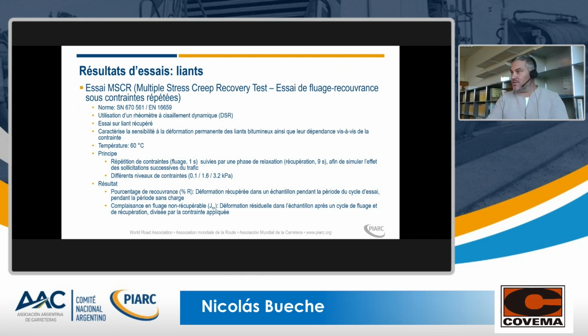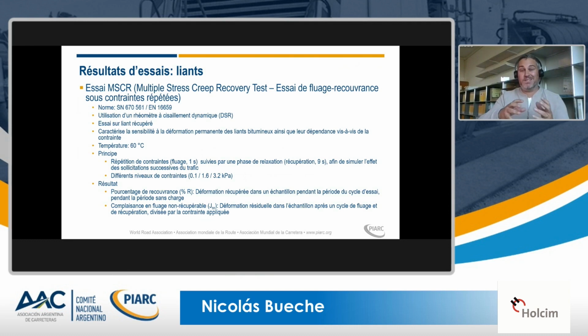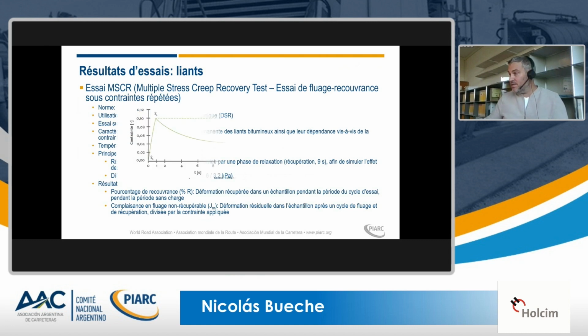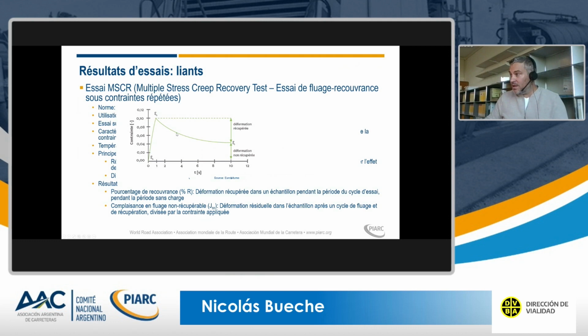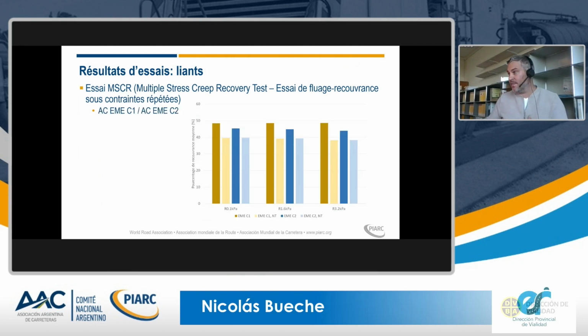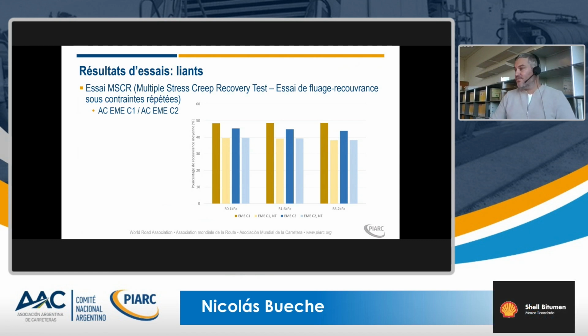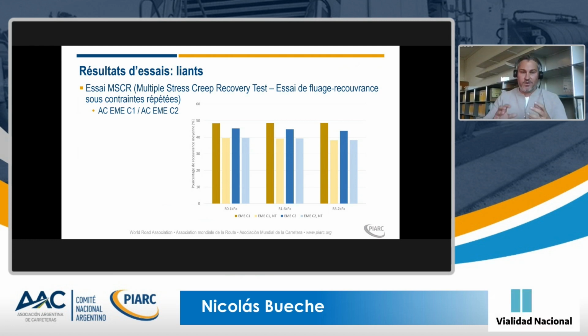We also made some other tests. We made some multiple stress creep recovery tests. That's basically a way to assess the rutting susceptibility of the binder. We still do it using a DSR method, and the principle is quite easy. We have loading and unloading phases, and we measure the deformation, the recovered deformation, and the remaining deformation of the binder. By using this, we could see some difference between the hot mix and the warm mix, which are the dark bars. It was quite surprising to us that we have a better behavior for the hot mix than for the warm mix, and it was quite interesting to see this, which might be related to the high modulus asphalt mixture.